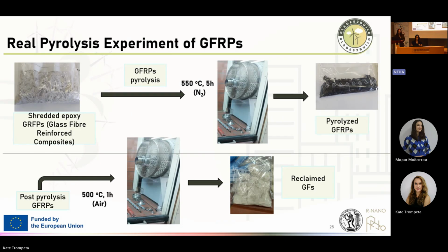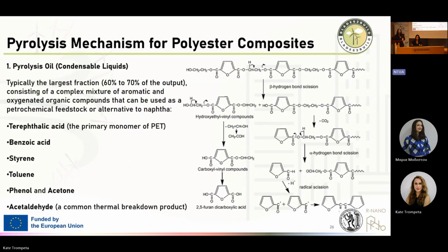Similarly, glass fiber reinforced polymers can be pyrolyzed. In our experiments, we had shredded epoxy GFRPs. So it was not the whole part, but shredded parts. Again, the reaction took place at 550 degrees Celsius for 5 hours under nitrogen. And then again a post-pyrolysis, in order to remove the char that is deposited on the fibers, at 500 degrees for 1 hour in air. So this methodology can also recover both chopped fibers and whole parts.